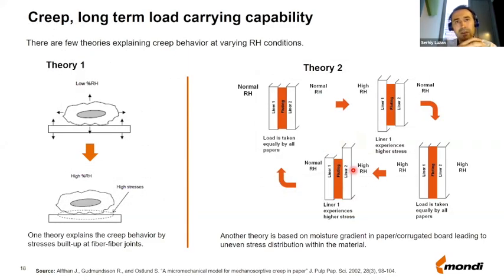Then you may ask, what is actually the theory behind the creep? Behind the creep, we have two theories. One theory is on the fiber level. The fibers in the paper are crossing each other, and at this crossing they form bonding between themselves. When the humidity is changing, fibers are either swelling, absorbing water, or releasing the water and shrinking. And the fibers shrink much more in the cross direction than they do in the length direction. Therefore, at these crossings, as you are cycling the humidity, some stresses are being built up because fibers are not shrinking the same way. As you are cycling, these stresses are weakening the bonding between the fibers, resulting in lower strength of paper and the boxes.